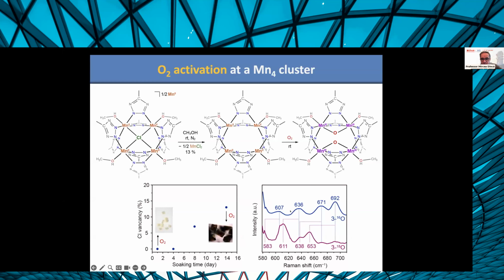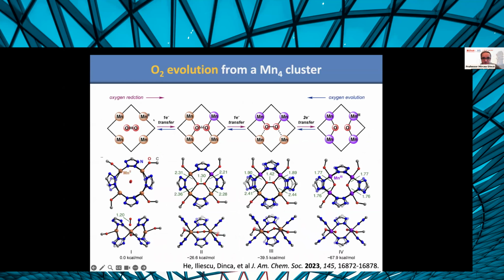You can do vibrational spectroscopy. I don't have the time to go through this, but you can label the oxygen that you react with your manganese MOF, and you'll find that what you make is actually breaking of the O2 bond into 2 dimuoxo compounds. So basically, we're activating O2 in making 2 oxo compounds, thereby oxidizing the manganese 2 to manganese 3. What was even more interesting is that if you heat the material, you actually make O2. This is extremely unusual and extremely difficult to do for any material, homogeneous or heterogeneous, and it is indeed what gives rise to life on Earth, incidentally, I would say coincidentally, also through a tetramanganese cluster in photosystem 2. So making this OO bond has specific spatial and electronic requirements that this MOF enables because of its site isolation.